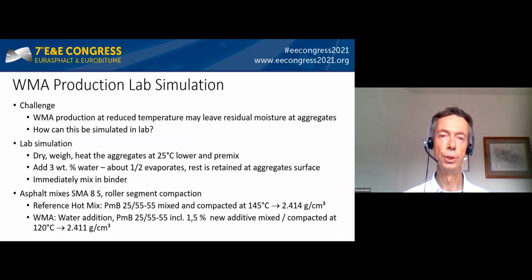Warm mix asphalt production at reduced temperature may leave residual moisture at the aggregates. But how can this be simulated in the lab? Laboratories generally are working with completely dried aggregates to get the mass balances correct. Our solution was as follows. The aggregates were dried, weighed, heated to 25 degrees lower temperature and were pre-mixed. Then 3% water were added. About 1/2 of the water evaporated and the rest was retained at the aggregate surfaces. Immediately after the water, the binder was added and the asphalt was mixed.